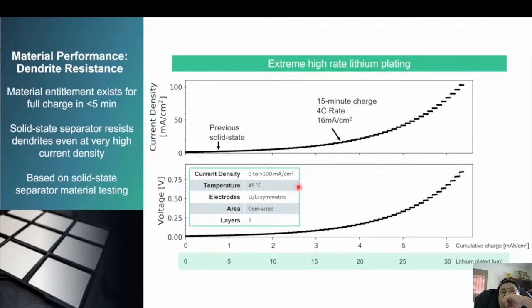This test was done at 45 degrees because that's really the condition probably most relevant to fast charge. I think in most fast charges, the car will already be driving, so the batteries will be somewhat warm, and then they'll also heat up due to their internal resistance as you charge. So 45 degrees is a pretty relevant fast charge condition.